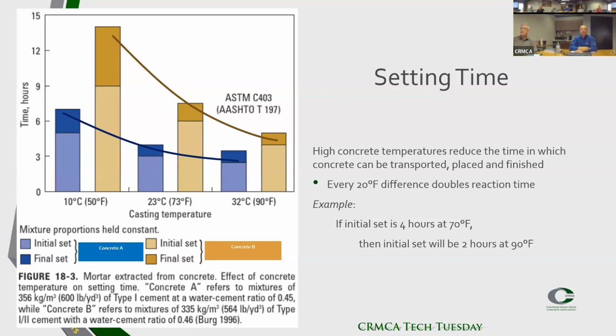Setting time, that's quite a busy graph, I know, but what we see is we have a concrete A, which is the blue concrete that shows the initial and the final set at different temperatures, 50, 73, and 90 degrees. And we see that as the temperature increases, the set time decreases. Concrete B, which is a different concrete, just two different mixes. And we see there's quite a big difference between the set times. The general rule of thumb is for every 20 F difference, you double the reaction time. This is basic chemistry, and it also works here for the set times.